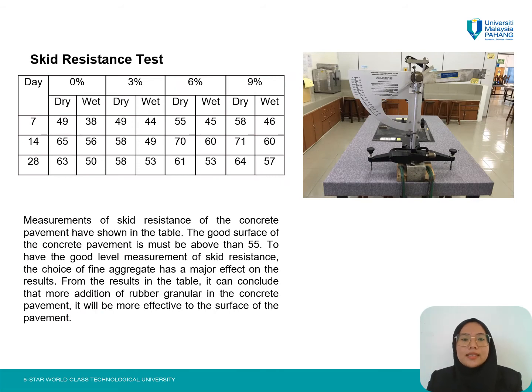Then this is the skid resistance test. Measurement of skid resistance of the concrete pavement is shown in the table. A good surface of concrete pavement must be above 55. To have a good level of skid resistance, the choice of fine aggregate has a major effect on the results. From the results in the table, it can be concluded that the more rubber granular added to the concrete pavement, the more effective it is on the surface of the pavement.